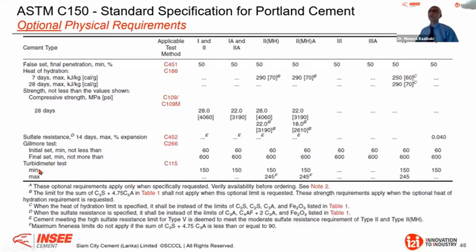And they also have a Blaine test or the turbidimeter test, where they give some limitation, because this is what I always say to my colleagues when we talk about Blaine. Normally the air permeability Blaine test is for OPC, really OPC, but when you come very often to compare them with some particle size distribution, it is much better to measure particle size distribution than Blaine. That is important that I can mention here also. Therefore, that is about the C150, and as you could see, the C150 is really OPC, 5 main type products: general use, moderate heat, moderate sulfate, high early strength, low heat, and high sulfate resistance.